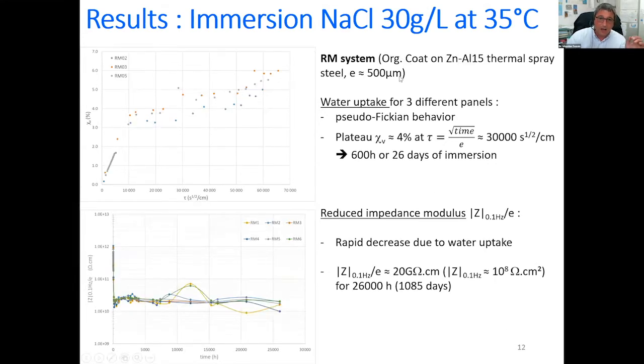Now the results for the RM system, it means organic coatings on the thermal spray, zinc aluminum thermal spray coat. We've got similar results with a rapid absorption of water, then a plateau at about 4%, and then a slight increase of this parameter. And if we look now at the reduced impedance modulus, we've got the rapid decrease and then a quite constant value all over the immersion period.